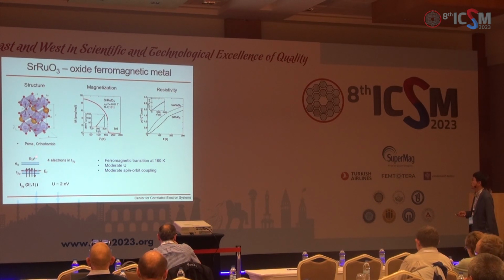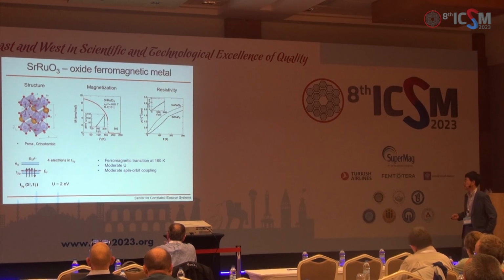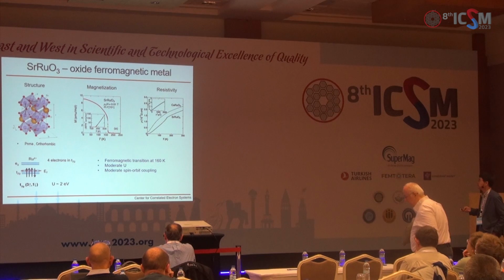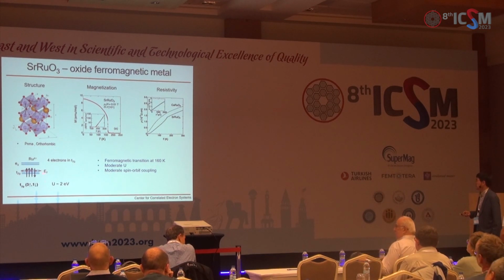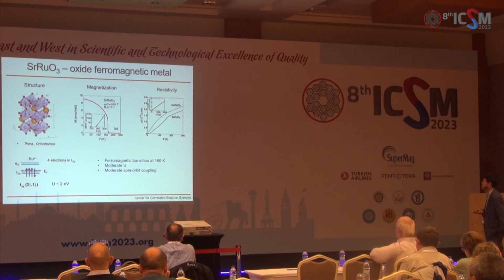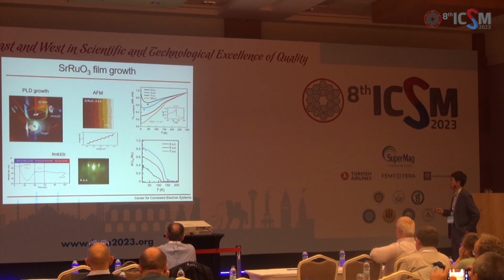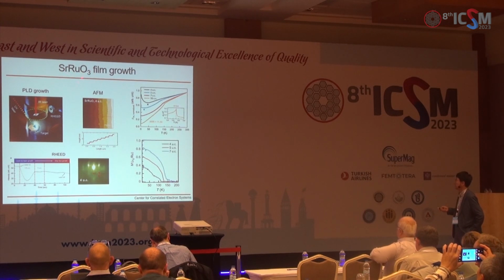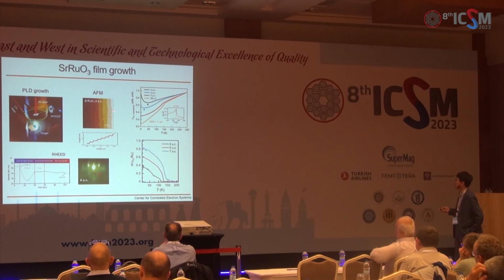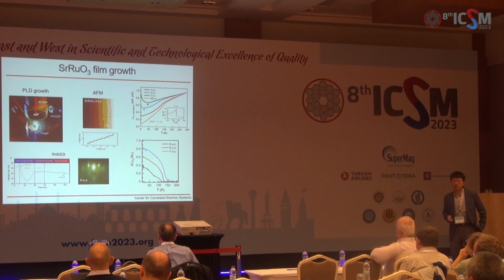Ruthenium is in the ruthenium 4+ configuration, so there are 4 electrons in the t2g orbitals. So the magnetic moment for ruthenium is around 2 or something, slightly smaller, due to a mixture of local magnetism and itinerant magnetism. And it has moderate U as well as moderate spin-orbit coupling. So we grew thin films of strontium ruthenate in PLD, and 4-unit cell strontium ruthenate shows very nice terraces. That means strontium ruthenate grows in something called the step flow growth mode.